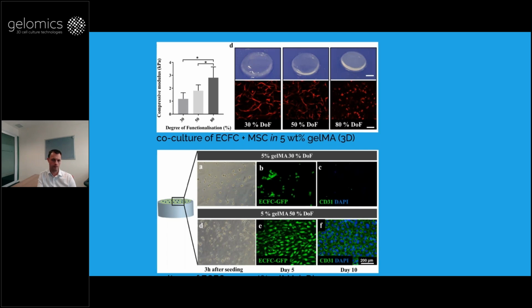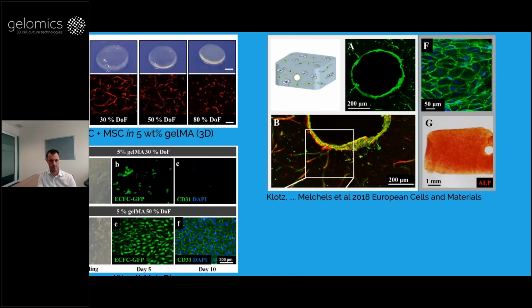And so we took that one forward to make this very simple model, just a block of gel. In the bulk, we saw capillaries forming. We see that endothelial cells had lined a channel in the middle, so you can see that lining. And we even saw anastomosis, so the capillaries would connect to that endothelial lining in that channel. So that was pretty nice.